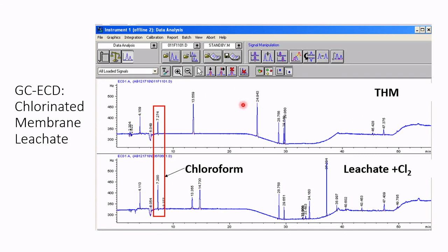They react on the instrument, and do they align with any of these unknowns that came from our sample? And at 7.2, there was a match for chloroform, which is one of the regulated THMs, trihalomethanes. There are several other byproducts here that have not been identified yet, and we're working on those right now, but an ECD is not able to tell us, similar to how the UV is not able to tell us structure. We need to take this sample on a GCMS so that we can speak to the structures, the mass spectra of some of these, but we're in the process of others.